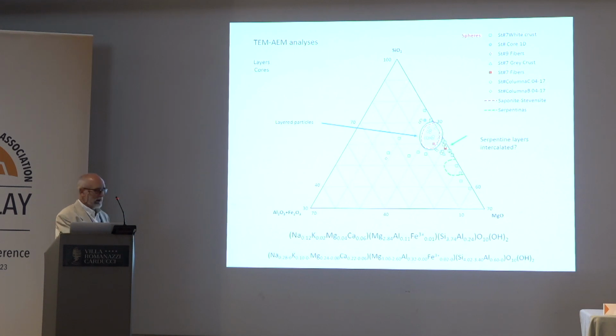Most of the analysis corresponds to amorphous and crystalline material. But in the crystalline layer, like here in this area where the saponite is still present, some of the layers are a little enriched in magnesium. We may think of an intercalation of serpentine layers, or maybe also magnesium hydroxide within the layer. We cannot be sure because the crystallinity is extremely low.